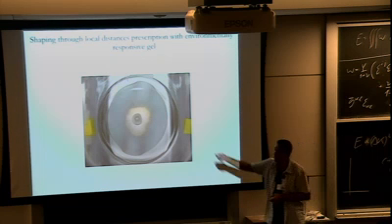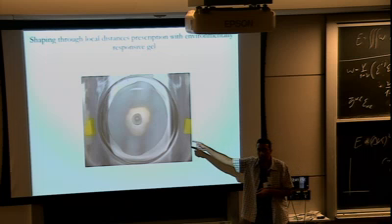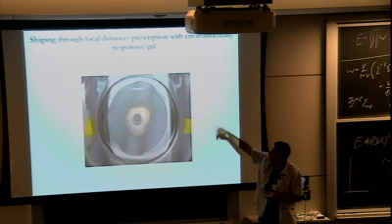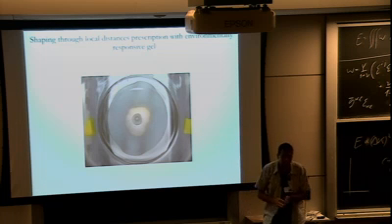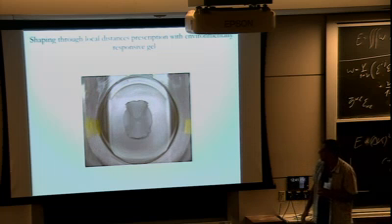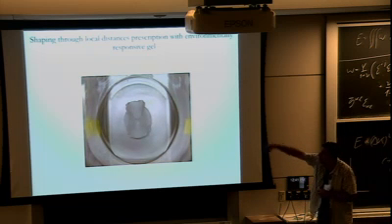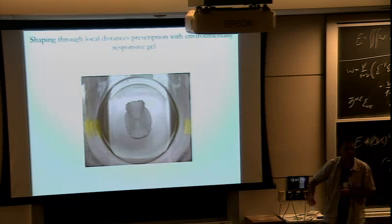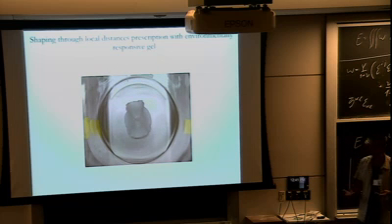So this is a movie of the heating up of such an object, which has the opposite, a hyperbolic metric. You can see it's very dilute at the center, so it's going to shrink a lot in there. It has a very dense exterior, so it's going to shrink very little. And you can see not only the ruffling, but the fact that it went into a saddle shape. And now we can cool it down, and it rehydrates, and it drinks everything up.